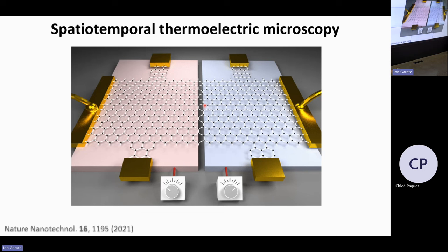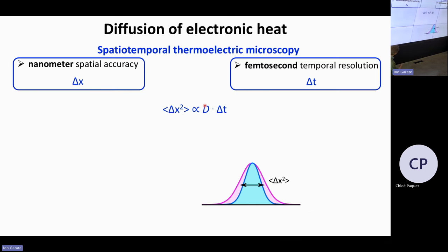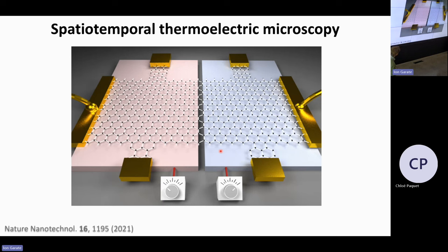In a way it's not a super resolution technique, but it's a relative super resolution technique, because you can imagine that if you have good enough signal to noise, even if this Gaussian that has a width of a micron broadens by a nanometer, you're going to see that broadening by just one nanometer. So your relative resolution of broadening is just limited by signal to noise. And in our case, we can get down to 10 nanometers of broadening of a one micron spot. So you cannot resolve very small features, but you can resolve very small amounts of broadening. We're still just diffraction limited.